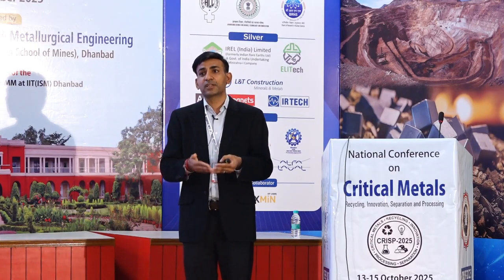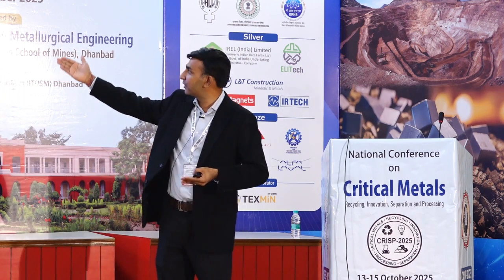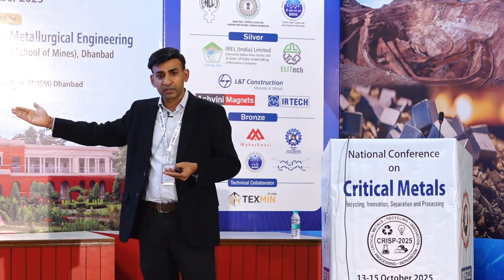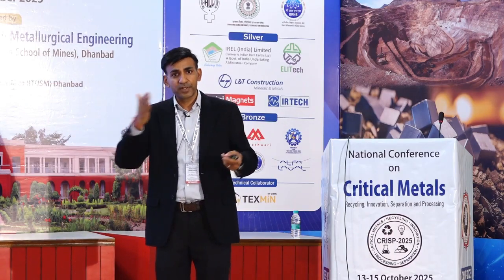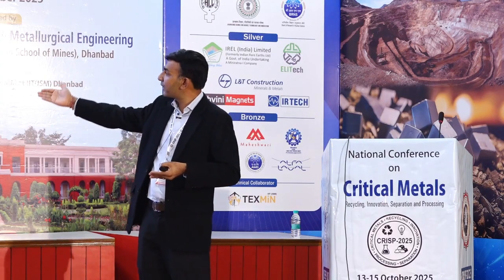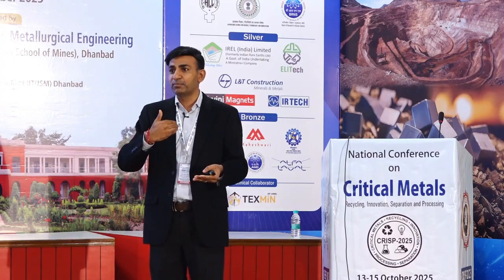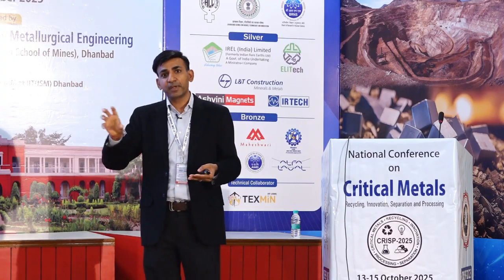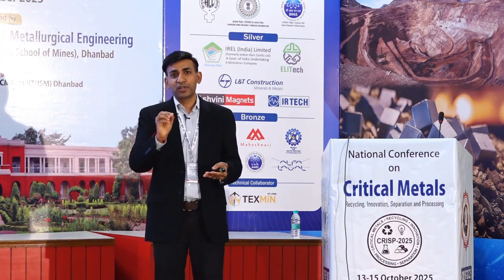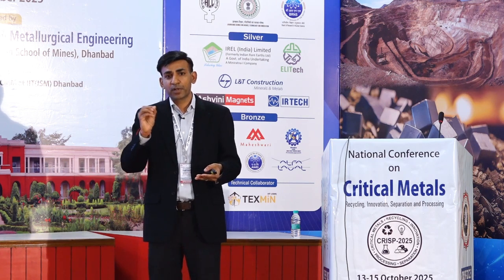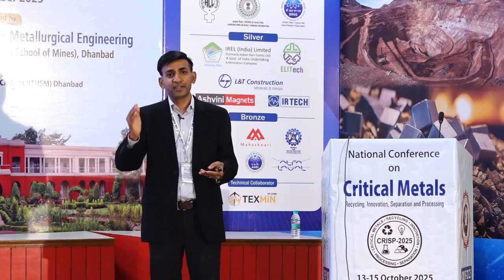Now this is where the process comes into the picture. You start with this first purified phase and do a further purification, which means a scrubbing. So first extraction, then scrubbing. When we do a scrubbing with a manganese-rich phase, you can get manganese of almost 99.9% purity. Now almost the entire cobalt is gone, and the nickel is gone. Obtaining a particular purity of metal is doable, but it requires a proper process. In some cases the number of stages or treatments may be 4, 5, 10, 100 times. In rare earth elements, the number could be up to 100.